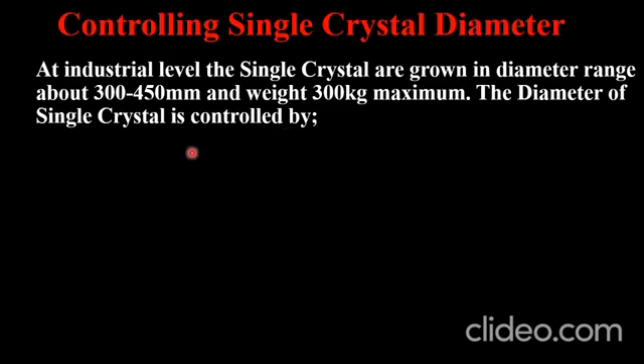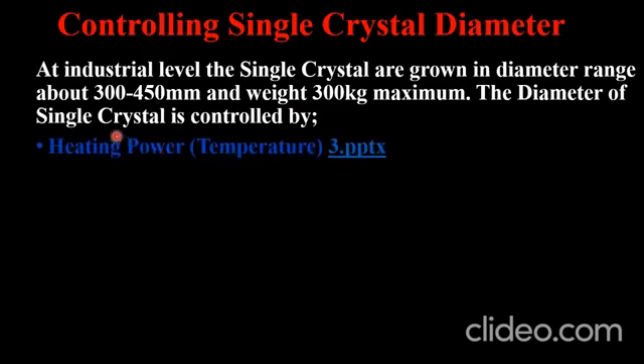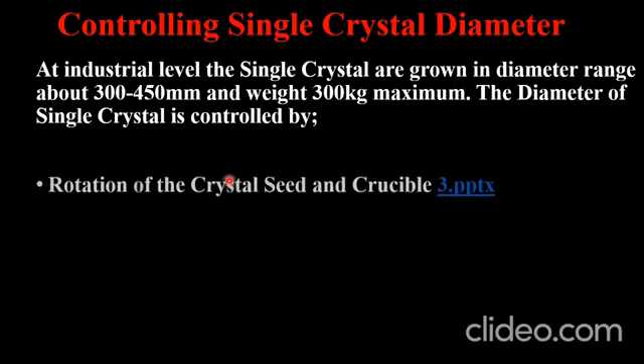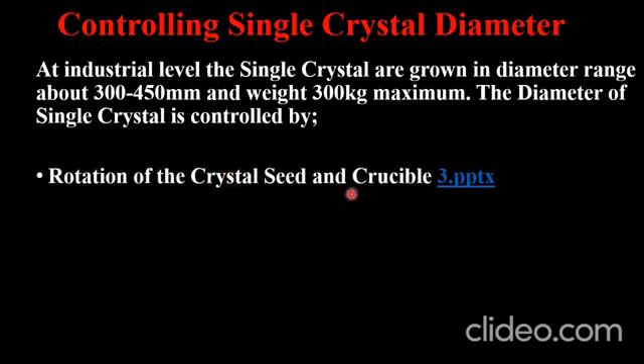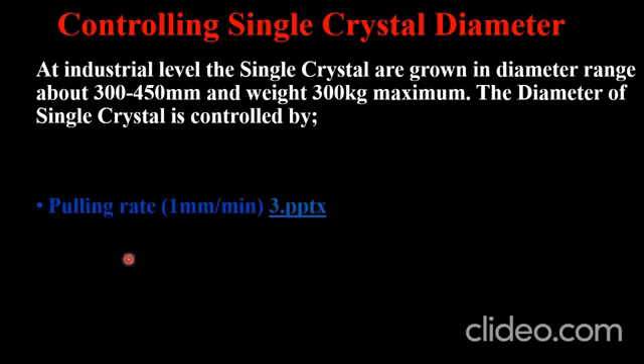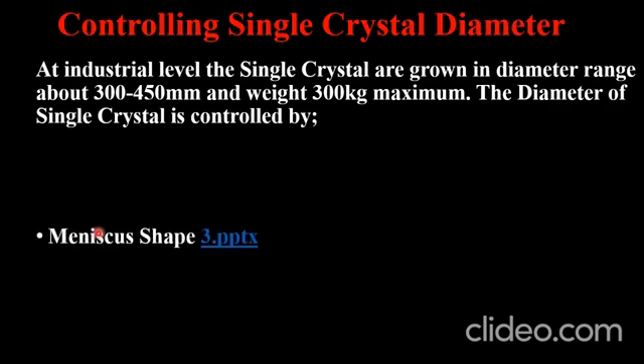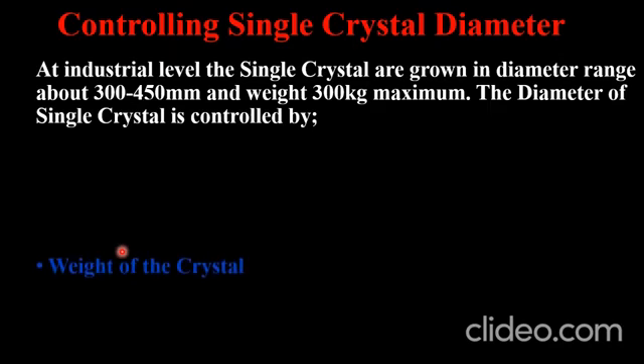The diameter and weight of the single crystal in industries is controlled by heating power. It is controlled by the temperature inside the chamber, and the rotation of the crystal seed and the crucible, which causes uniformity over the whole structure and also improves the quality of the crystal. Diameter is also controlled by pulling rate. The diameter of the single crystal is also controlled by the meniscus shape. Meniscus shape is basically the shape between the seed and the melt material. The diameter is also controlled by the weight of the crystal.